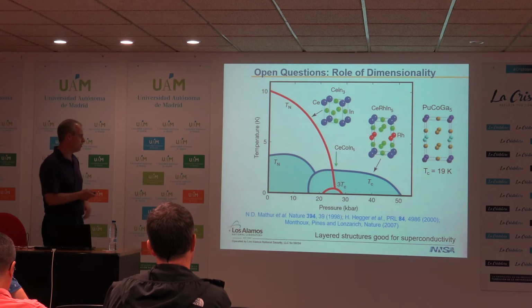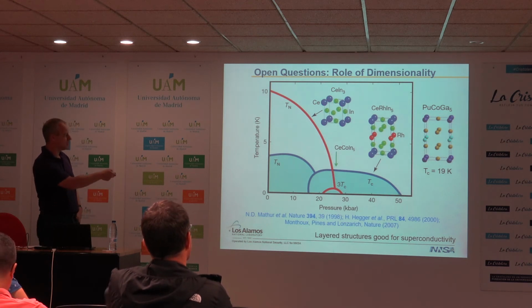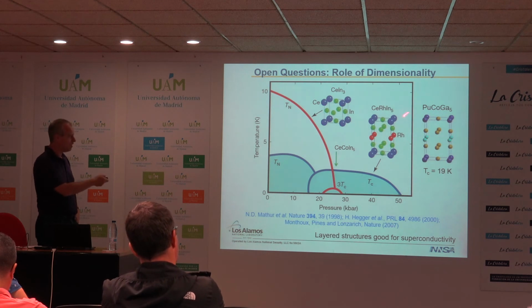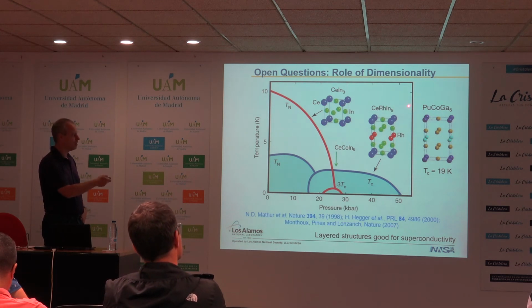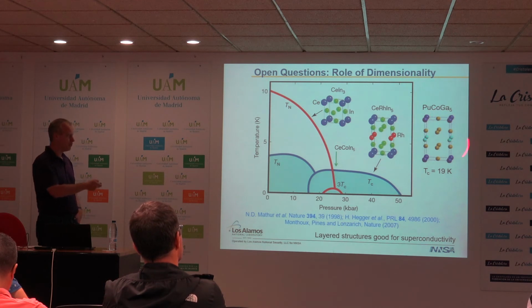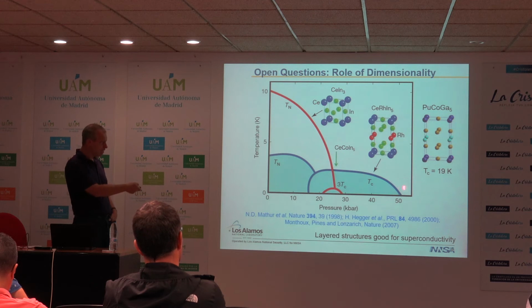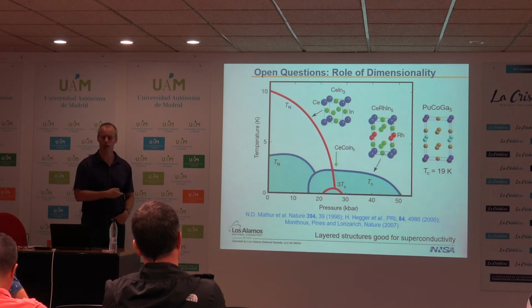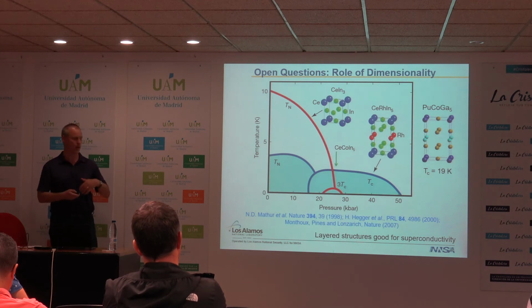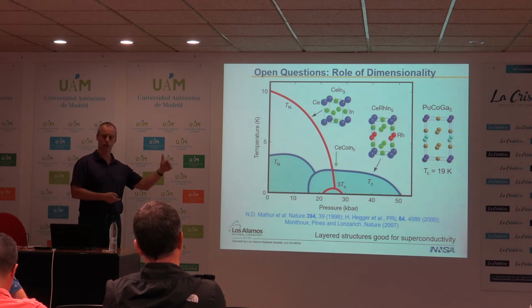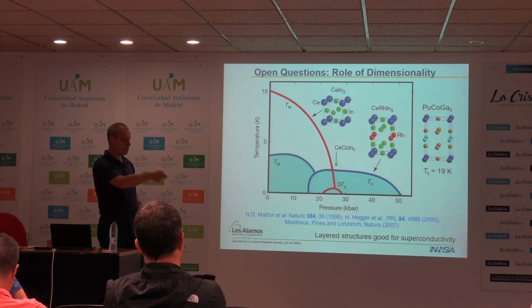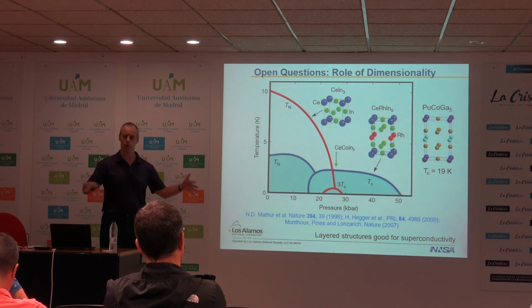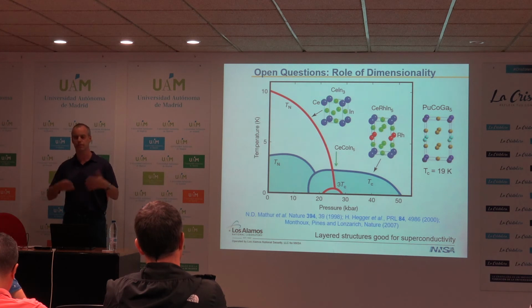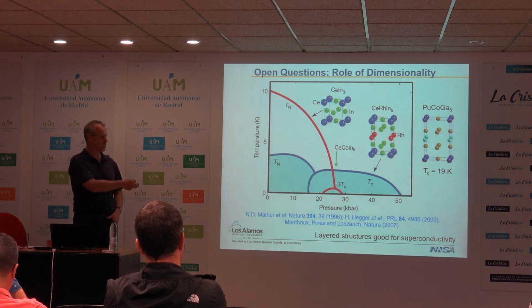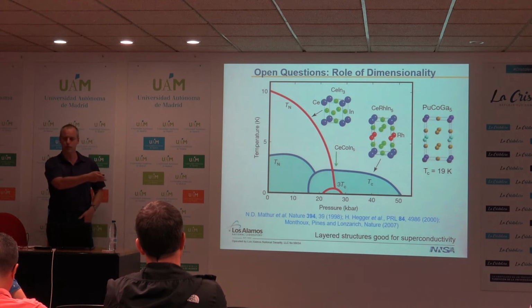Okay. The story, at least when you're at Los Alamos, doesn't end with cerium rhodium indium 5. In fact, you can make a plutonium analog of this system. Plutonium cobalt gallium 5 forms in exactly the same crystal structure and is in fact a nearly 20 Kelvin superconductor. So you went from 0.2 Kelvin to 2 Kelvin to 20 Kelvin, all within the same family. The very naive view here is that plutonium, being a 5f analog of cerium, has more extended wave functions, so larger degrees of hybridization, the spin fluctuation energy scale is larger, and that's boosting TC another order of magnitude. So we have two orders of magnitude increase in TC.